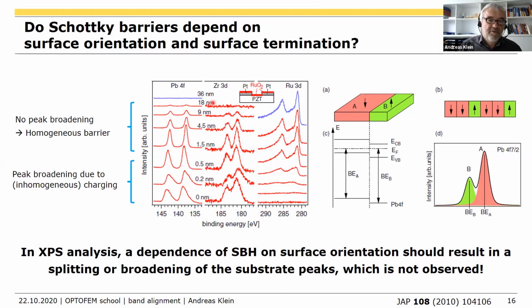But as soon as you put your ruthenium oxide on top, you get an electric contact. You can contact the sample from the top, and that means you have no more charging because you can provide an electric contact from the top surface. And now the peaks are sharp. These binding energies are the same everywhere on the surface because we measure a square millimeter. And if you get a sharp, symmetric peak, we know that the Schottky barrier is everywhere the same.